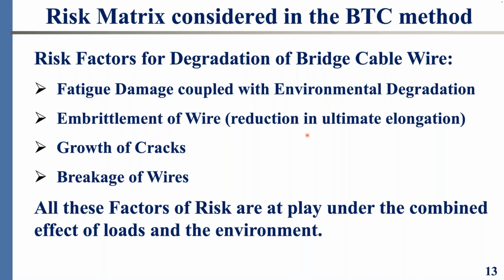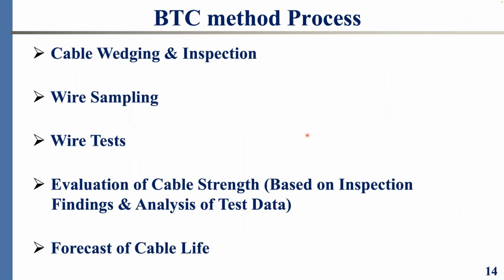So the BTC method process starts with cable wedging and inspection, wire sampling afterwards from each cable opening. By the way, when we say cable opening, that basically defines the length of cable between two successive suspender ropes. So we call it cable opening, panel, cable length, and inspected. All this boils down to the distance between two successive suspender ropes. So we take the wire samples that we're going to take a look at now, and take them to the lab, chop them into pieces, have the wire tested as we're going to see later on, and then take the test results, the findings of all the inspections, and do the analysis, get the strength of the cable, and then identify the cable strength today, and then do further analysis based on the data to forecast the cable life.